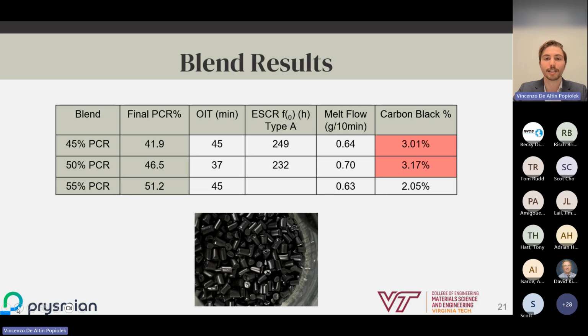For ESCR, which has an industry standard of 48 hours, with a type A tensile bar, a type A ESCR tab, which again is more strenuous than what is actually required, as only type B is required for this, we were still able to significantly pass the industry standards, surpassing it by 5 times for our 41.9% and almost 5 times in our 46.5% PCR blend. Testing was not performed on the 51.2% PCR blend during this semester due to time constraints.